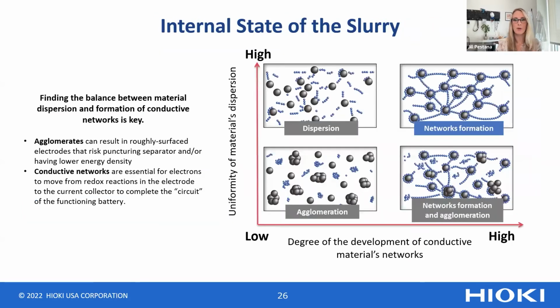So finding that right moment is so crucial. Finding that balance between material dispersion and formation of conductive networks is key. And here's a graph to display that. And those agglomerates that start with low amounts of mixing can actually result in a roughly surfaced electrode that could puncture the separator, causing a short circuit. So we're not just talking about making sure it's conductive, but also safe to use inside of a battery. And those conductive networks are essential for the electrons to move and complete the redox reactions.